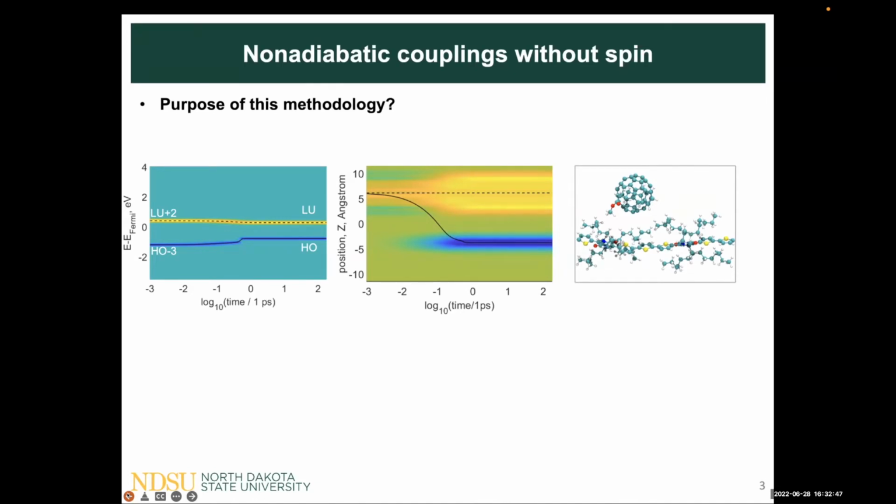But for sure, those systems are 5 to 10 times larger in number of atoms. Each side of that cube is around 3 nanometers, so they are pretty expensive and challenging models. And we are thinking how to actually quantify the charge transfer for such 3D systems. For sure, this kind of approximation or idealization will not work for that 3D model. So we need to find another way to visualize, or actually characterize, the charge transfer between the donor and the acceptor unit in the 3D system.